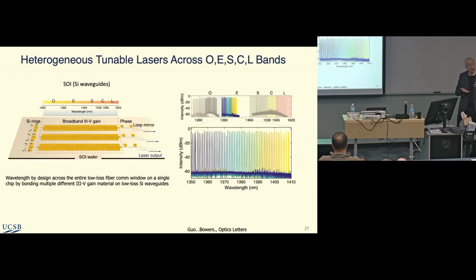One advantage when you bond materials is that you can bond multiple epis at one time. You'll see this in the next slide from Intel - they've done this from the beginning. They do CWDM, and for each PIC they bond 4 different epis to get wider range than you can get with a single epitaxial material. In their case, they go across 80 nanometers. We did even further, combining O band, E band, and then S, C, and L bands all in the same PIC.